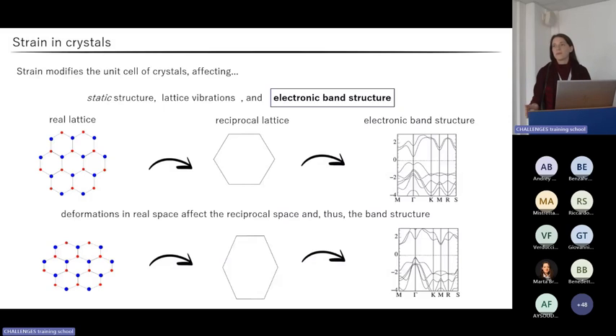In fact, it is well understandable that in a crystal, any deformation of the direct lattice is automatically mapped onto a deformation of the reciprocal lattice, and therefore it affects the electronic band structure of the system, which is the ensemble of all the quantum states electrons can occupy in terms of energy and momentum vector in the reciprocal space. In that case, we cannot rely on toy models in order to qualitatively predict the evolution of the electronic band structure of a crystal as a function of strain, but we need to perform accurate ab initio calculations at varying the lattice parameters of our system.